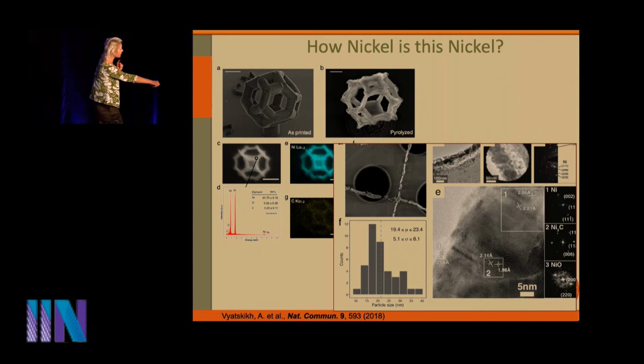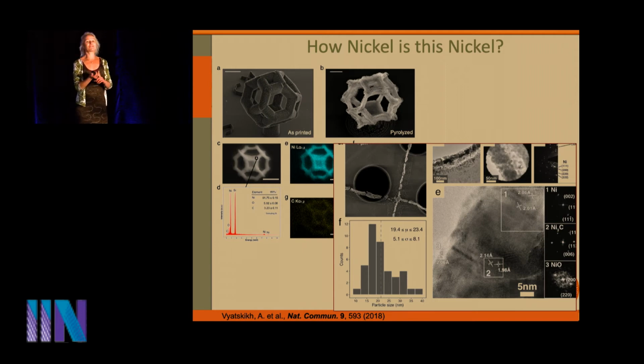So this particular pyrolyzed beam is, in fact, located over one of these holey membrane holes, and that's when we say, hallelujah, we do this every day. It's no big deal, works every time. Yeah, so what's really nice about this is that this particular sample has never seen the FIB, has never seen any damaging ion effects. It's as-manufactured material. So everything we see is a result of this process.